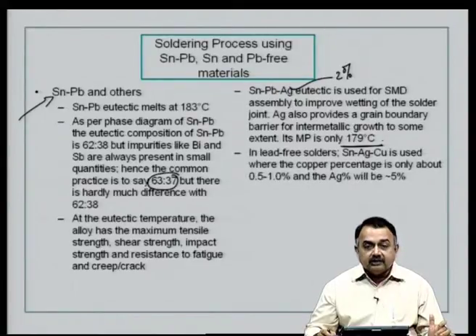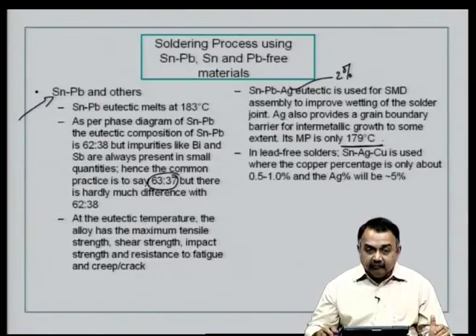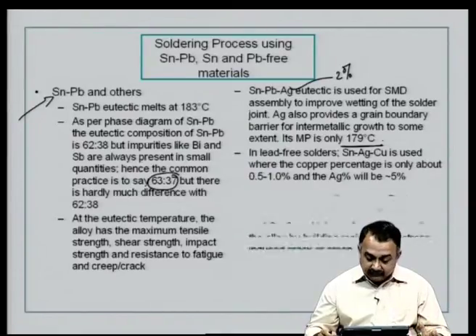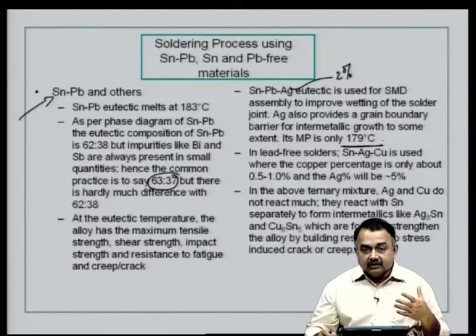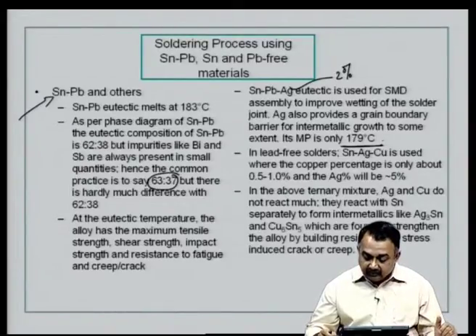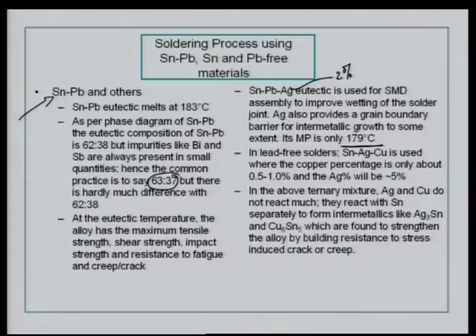In lead free solders, tin silver copper is used, okay, very popular, where the copper percentage is only about 0.5 to 1% and silver will be around 5%. In the above ternary mixture, that is the tin silver copper ternary mixture, silver and copper do not react much. They react with tin separately to form intermetallic phases, like Ag3Sn or Cu6Sn5, which are found in literature to strengthen the alloy by building resistance to stress or fatigue or stress induced crack or creep, which means the reliability of this system is definitely much better compared to other systems.